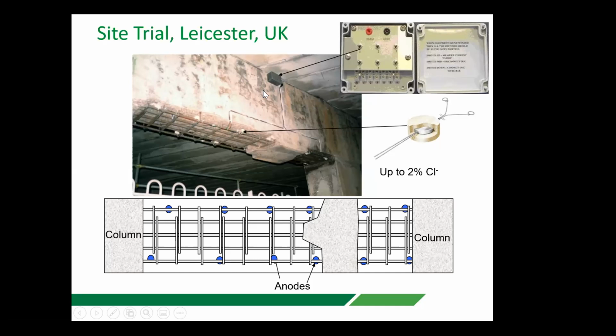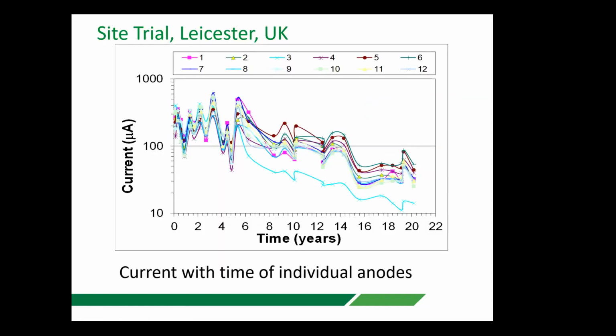That allowed us to measure the current that flowed between each individual anode and the steel. It also allowed us to turn off the system for 24 hours and watch how depolarization would develop over time, and also look at the depolarized potential 24 hours after disconnection. And this is essentially the current output that we saw over the years of each individual anode. 12 anodes there. You can see that one of these is not particularly happy, but all the others are more or less diminishing in intensity with time.